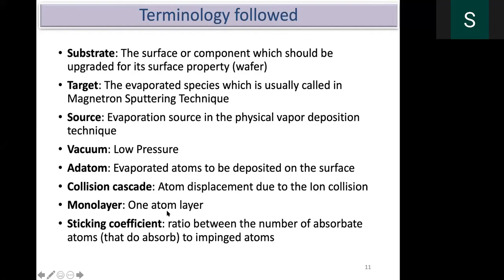Monolayer: fundamentally, thin films can be grown by island growth or layer growth, or both together. When you cover the full surface, one full layer forms, and that is called one monolayer, one atomic layer. And sticking coefficient is the ratio between the number of adsorbed atoms to the impinged atoms. See how much goes and sticks to the surface: many atoms go, but only a few atoms stick. That is the sticking coefficient. So not all evaporated atoms will go and stick to the surface of the substrate.